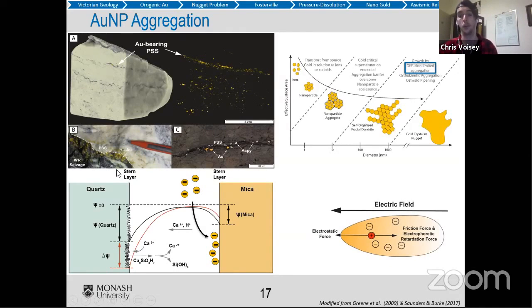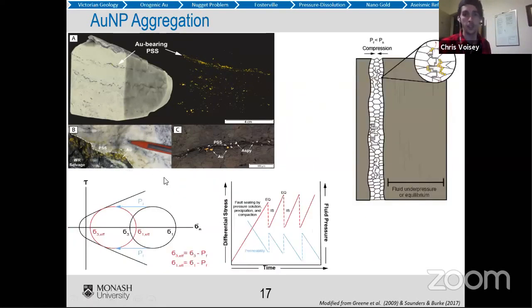So I think this is an example of what is called diffusion limited aggregation. We basically put charged particles under an electric field, and they're negative, they like positive, they just stuck to it. They're in this solution during pressure dissolution, so at the grain boundary contact. If you're going to float a charged particle through it, it's going to stick to the oppositely charged surface. So this again happens during the interseismic phase. You have to have your locked up fault at this point. So now we've gone from having gold sprinkled in a vein to removing the material we don't like, and then having gold stuck to this wall rock magnet that was in the way.